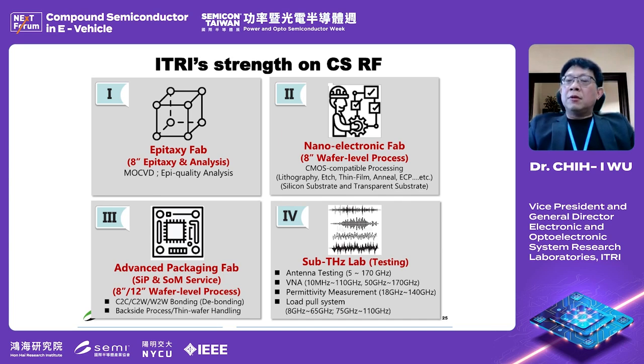We also, in the past three to four years, built up a very good state-of-the-art sub-terahertz lab testing system. We can test antennas up to 170 gigahertz, and we can also do material measurement all the way from a few gigahertz to 140 gigahertz. Those are essential lab testing equipment for high frequency electronics development.